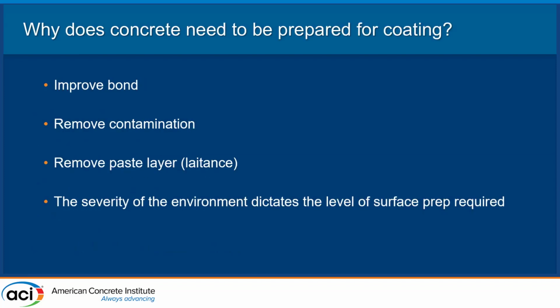So why do we want to talk about the surface preparation before actually applying these coatings? The main thing is to improve the bond. If the surface is not prepared correctly, the coating will not adhere correctly, and then again the surface life will be severely reduced. Also, contamination. We'll talk a little bit about the contamination that can be on concrete that could inhibit the adhesion of coatings. And then we want to talk about removing the latents, or the paste layer, which is the very thin film at the top of the concrete that has very little tensile strength that can also affect the adhesion. And then a rule of thumb that we have is the severity of the environment dictates the level of surface prep needed. The more robust coating, the thicker the film of the coating applied to the concrete will require more extensive surface preparation, more surface profile, and we'll talk about that a little bit more in just a moment.